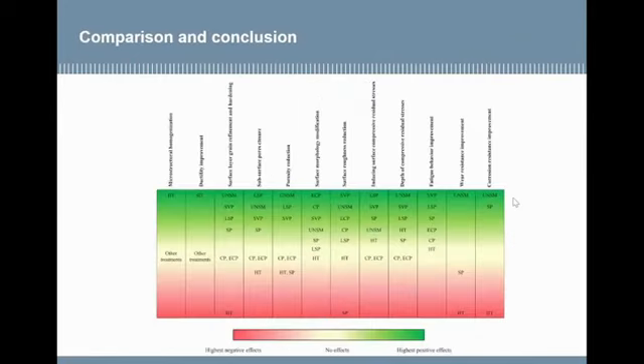Just to conclude here, I'm showing the fact that there is a large range of parameters that can be modulated by post-treatment in terms of the microstructure, in terms of hardness, fatigue, wear, corrosion, and the different functionalities of the samples. And depending on the geometry of the sample, the cost and the type of the material and the target application, these post-treatments should be tuned in order to get the best results.